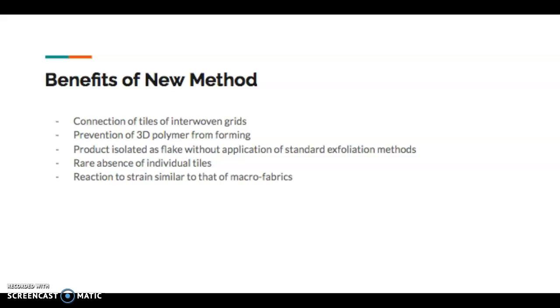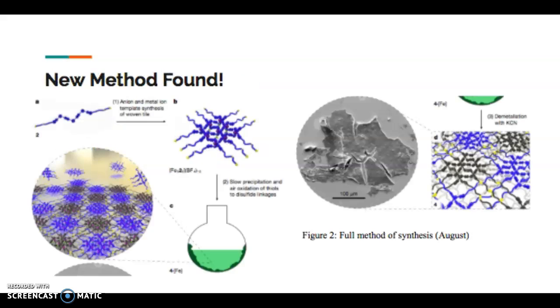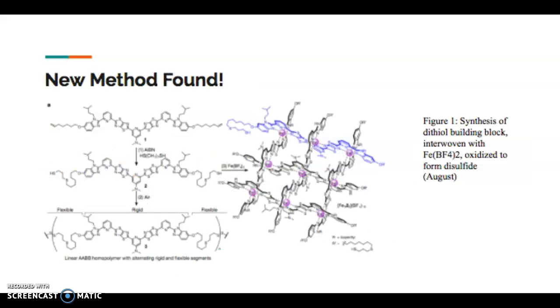the woven architecture and long-range order allowed the two-dimensional woven nanofabric to react to strain in a similar way to macroscopic fabrics, specifically cracking along clear lines and slipping between layers. Also similar to macroscopic fibers, this nanofiber had a box weave pattern, which we covered before and which you can see here with it alternating up and down. And it was loosely woven but had flexible and rigid segments.